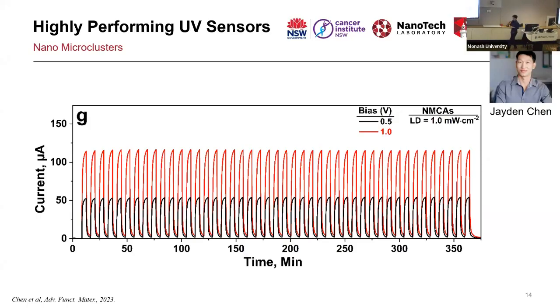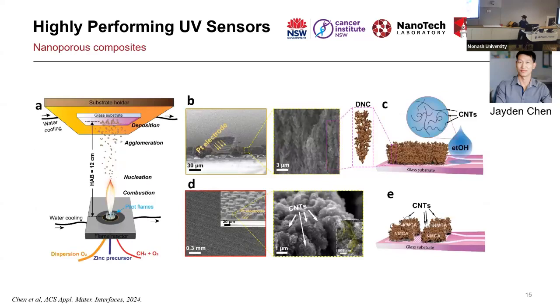And as you can see, the sensor is very stable. This is just a chunk of the test that I cut from the sample, but we could run it for weeks, switching on and off every time, and you actually end up with the same results. So that was the main discovery. But then it gives us the opportunity to add anything we want into the system.